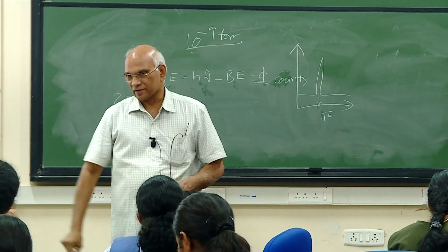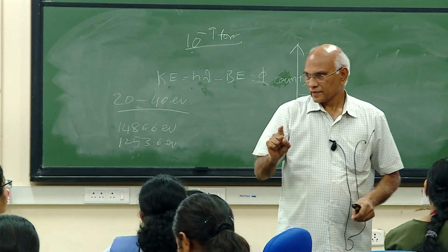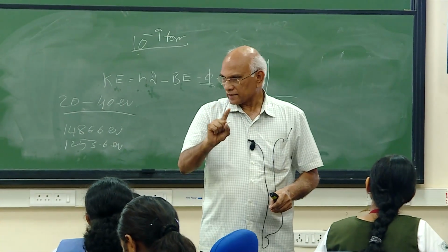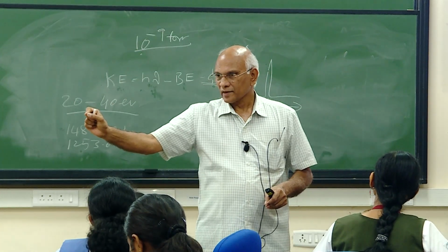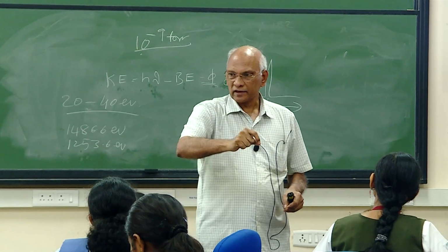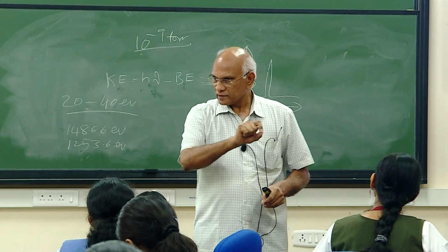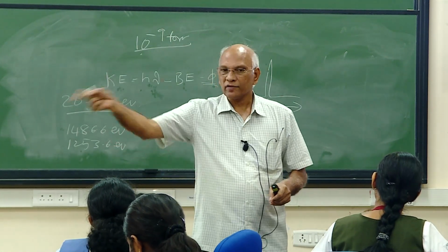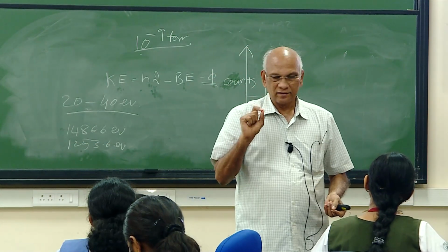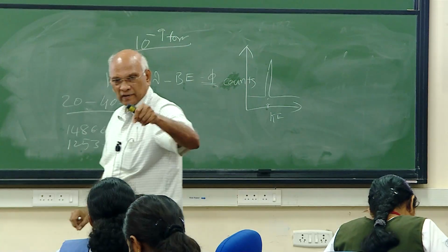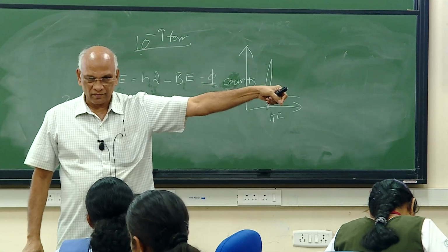you have in the first row transition metals. So in each of these atoms, if you see a d electron, is d electron of course, but then in each atom the d electron will have different energy. Right? So you remove an electron from titanium or vanadium or chromium, same d electron, but it will have a different binding energy, different kinetic energy also. So you measure that, right? So then from that you can figure out which element it is coming from.